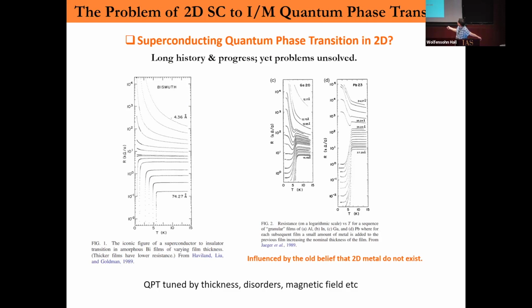There's, for example, in this case, there is residual conductance. And there are many, many of these reports. So the superconducting quantum transition, not tuned by temperature, can be tuned by the thickness of the material, disorder, or magnetic fields.